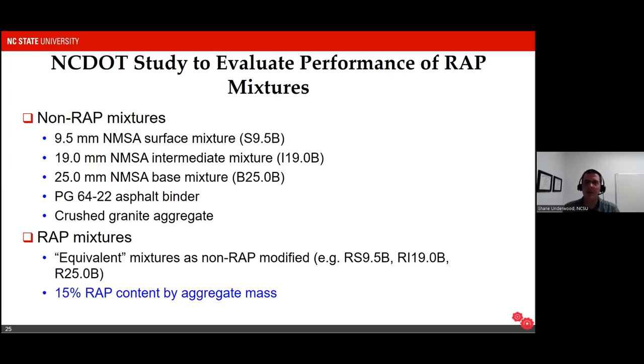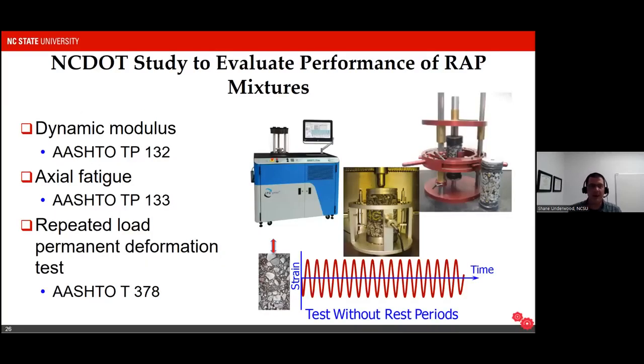Now, if we wanted to look at the performance of the RAP mixtures, we had to do a series of laboratory experiments. So what we did were AASHTO TP 132, which is dynamic modulus testing. We did axial fatigue testing and permanent deformation tests. We basically wanted to figure out how stiff the materials were, how likely they were to experience fatigue cracking, and then how likely they were to rut and permanently deform. I'm not going to get into the details of how those tests are conducted. I hope you're somewhat familiar with, if not the tests themselves, at least the idea that we need to understand the modulus of the material, the fatigue resistance, and the permanent deformation resistance.